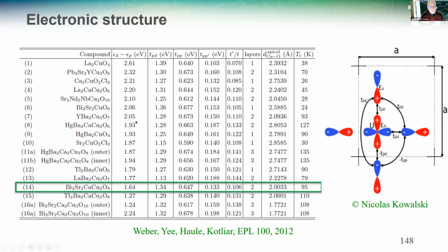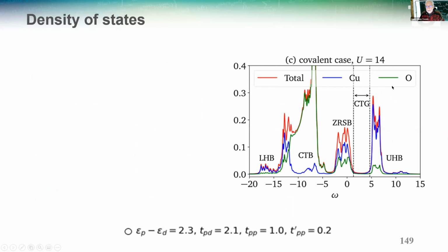If you look at how the parameters vary, it's not that much, basically by a factor of 2 or even less in some cases. If you stare at this, don't look at T prime over T, but at TPP prime and all these parameters: they don't vary that much, but they do vary. So this is the covalent case I just talked about. Compared with the ionic model, the lower Hubbard band is sort of merged with the charge transfer band, and the charge transfer gap is still there. The parameters now are TPP equals 1 and epsilon P minus epsilon D is 2.3. So that's our starting point.